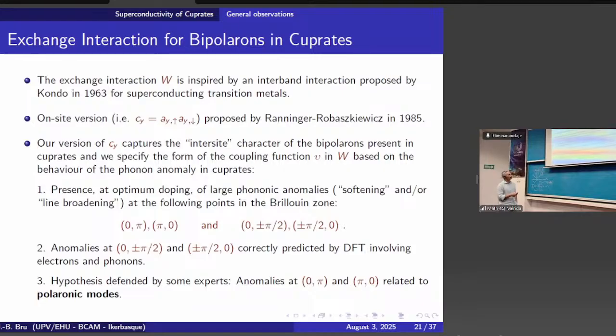This one is well reproduced, so with some density functional theory, they try to reproduce this anomaly numerically. They are able to do it for this one, and not for that one. And this density functional theory does not take into account the existence of polaronic particles. So that suggests that if it reproduces this, there is no polaronic particle, because this is not included in their modelization, whereas this other one is a good candidate for that.